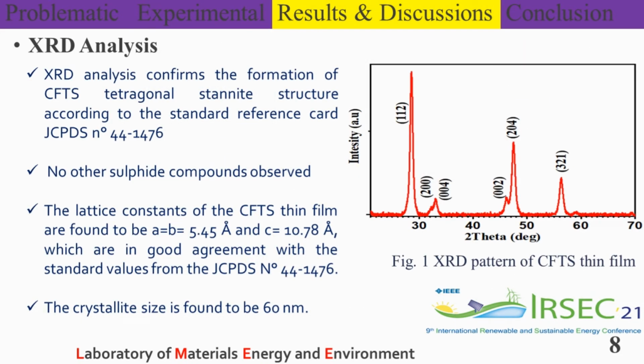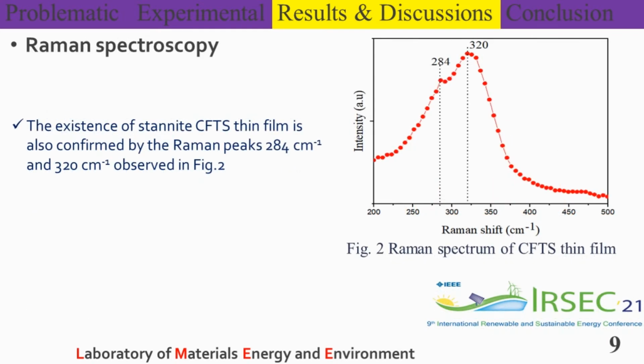For results and discussions, X-ray diffraction analysis confirmed the formation of CFTS tetragonal stannite structure according to standard reference cards, and no other sulfide component was observed. In addition, the lattice constant and the crystalline size have been calculated. The lattice constant values are in good agreement with the standard values from the reference cards. The crystalline size is found to be 60 nanometers. Also, Raman spectroscopy confirmed the formation of standard CFTS thin films.